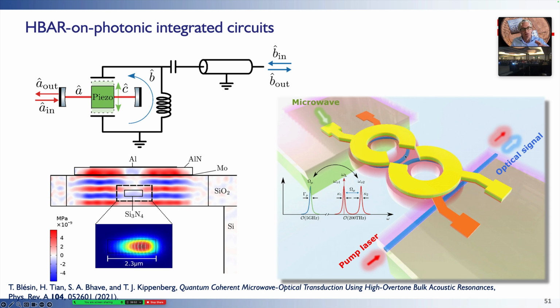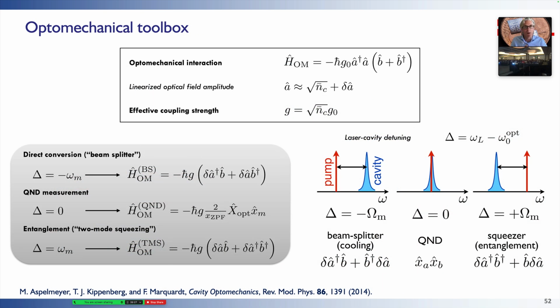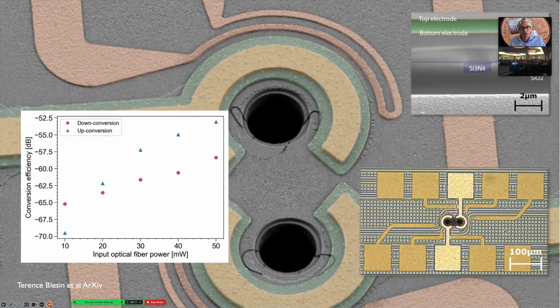What happens here is that the electrical signals convert to a bulk acoustic wave, which in itself is coupled back and scattered into a sideband of the optical pump, which is also resonant. So it functions here as a triply resonant transducer, resonant for the acoustics and also resonant for the two optical fields that are coupled via the piezoelectric effect. And these devices allow us to explore this so-called optomechanical toolbox that I only want to put there and glance over, but the optomechanical toolbox allows us to convert the mechanical excitation to an optical sideband or the optical sideband to mechanical excitation. And this technique allows us, for instance, to create devices as shown here, whereby we can convert optical sidebands to microwave generation or microwave radiation into optical sidebands. So it functions as a single sideband or single-sided acousto-optic converter, but in contrast to bulk devices, the efficiency can be exceptionally high.